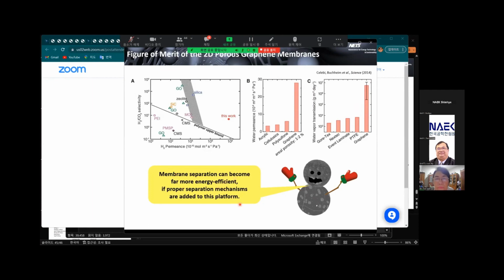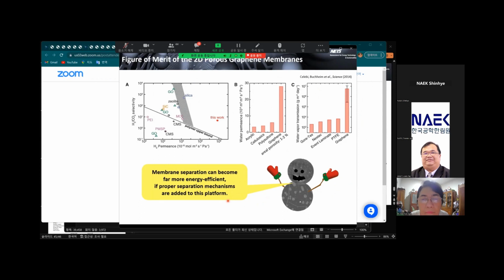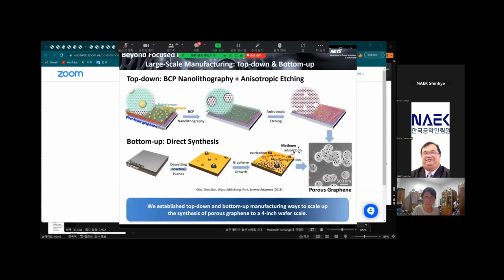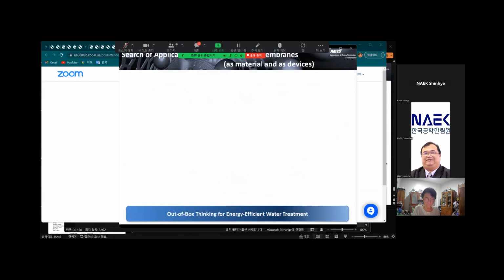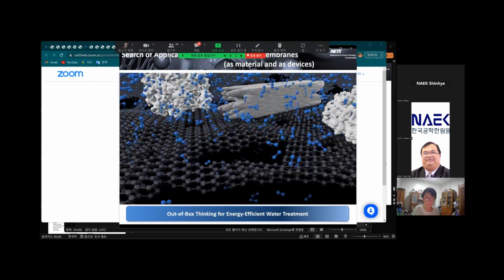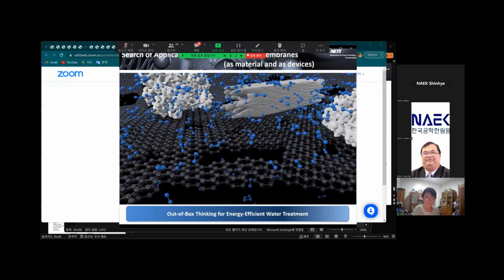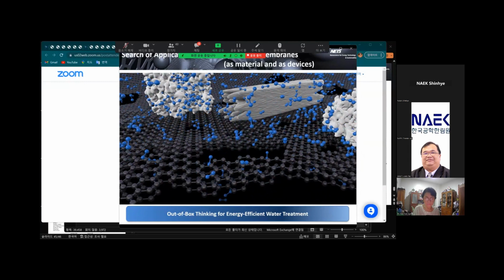Identified challenges to consider in further developments include addition of suitable separation mechanisms compatible with the high permeation membrane material, finding methods for scaling up the membrane manufacturing, sustaining in operando mechanical conditions, and assessment of concentration polarization and temperature polarization, to list a few. For overcoming the manufacturing hurdle and moving beyond the focused ion beam method, we have recently developed both top-down and bottom-up manufacturing methods of producing porous graphene membranes having pore sizes of few tens of nanometers. Efforts for understanding the zero-dimensionally confined transport physics and to find engineering applications of the high permeation membrane have just begun. To this end, out-of-the-box thinking is needed.